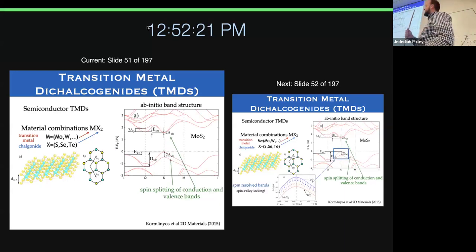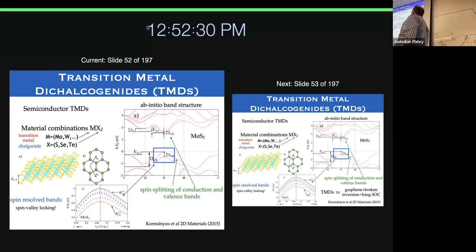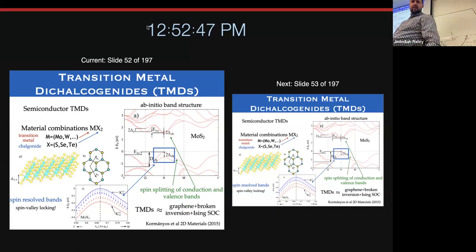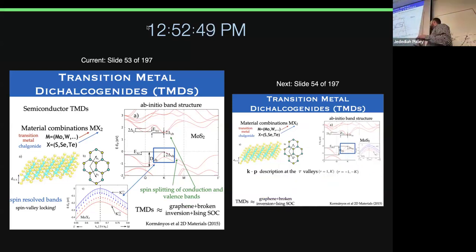You also see a spin splitting. This is due to Ising spin-orbit coupling, which you can then estimate the scale of. And if you look at the spin dependence of these bands, K is locked to spin down, K prime is locked to spin up. Okay, so that's called valley spin locking. The valley is locked to the spin. This is important, and we're going to use this to actually measure magnetic properties of these materials. Okay. And so you can think about TMDs as being like graphene with broken inversion and a large Ising spin-orbit coupling. That's the loose way you can think about it.